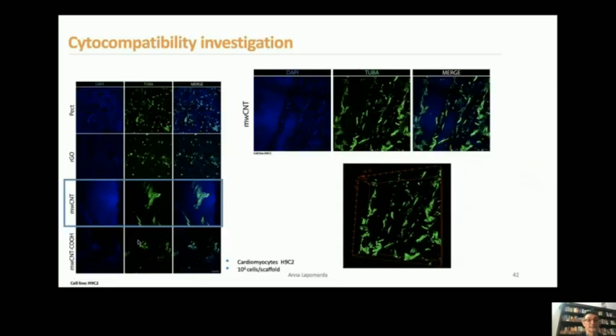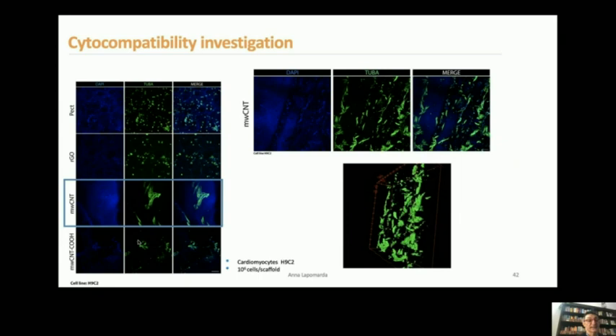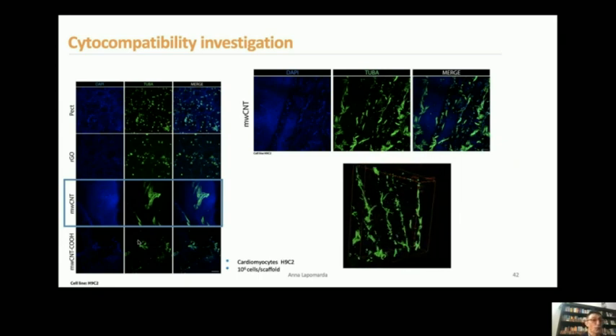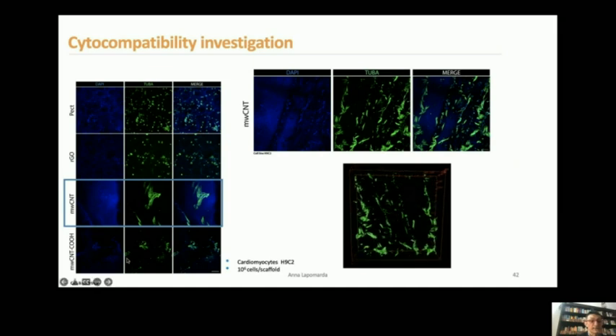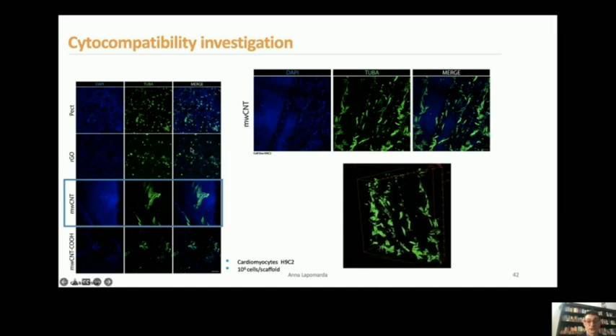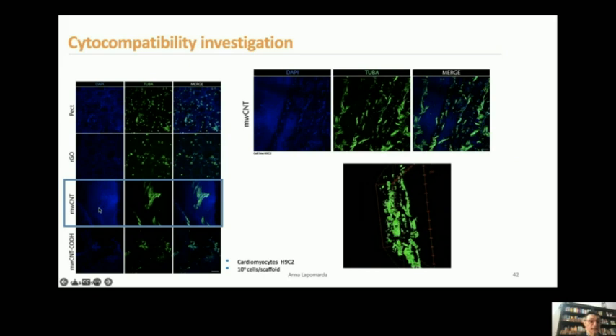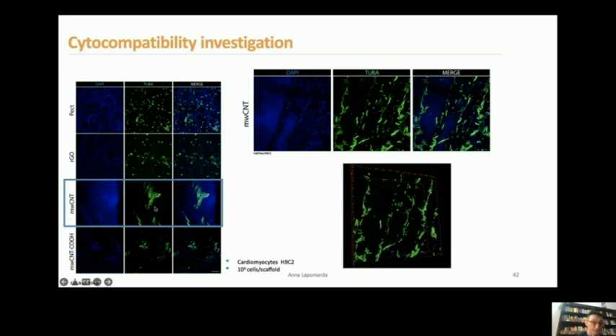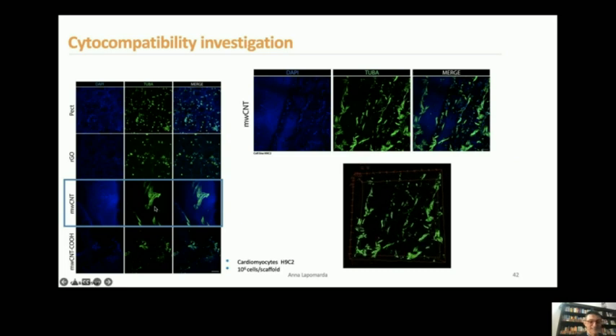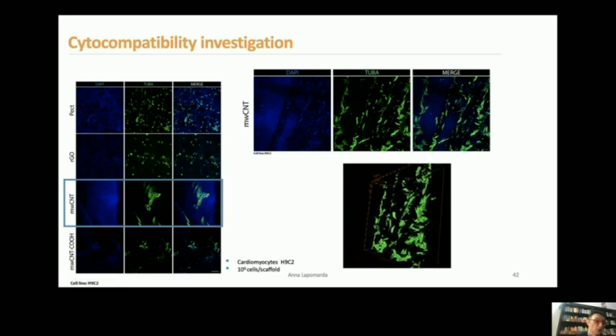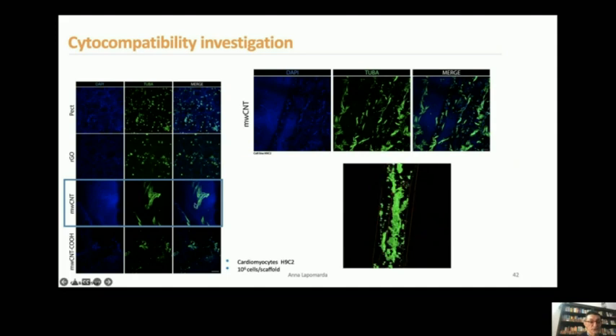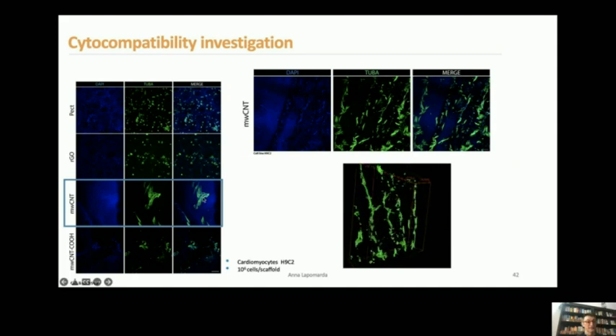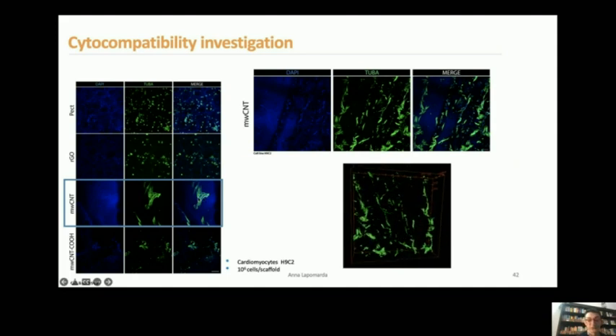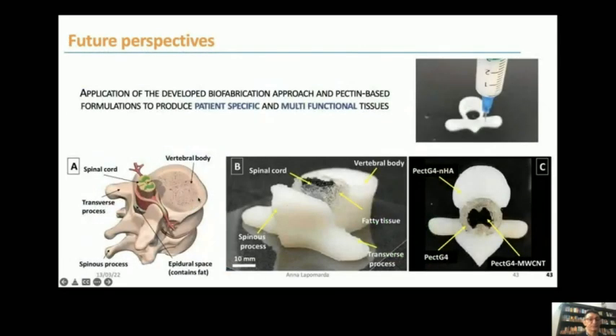On these materials, we seeded cardiomyocytes, and as you can see here, in all these scaffolds we have good adhesion and proliferation, but in particular, analyzing the scaffold with pectin, where we see that cardiomyocytes with the multi-wall carbon nanotubes had a more defined organization and formation of the cytoskeleton.